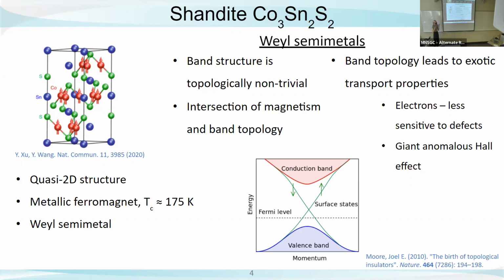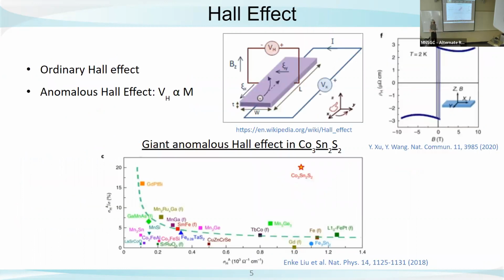And another thing that comes with Weyl semimetals is this giant anomalous Hall effect. And so a little bit on this Hall effect. When we measure an ordinary Hall effect, we take that material here in purple and we run a current through it. And then we apply a magnetic field and measure a Hall voltage transverse to that current that we're sending through it. And when we would get an output of magnetic field versus Hall signal for our ordinary material, you would see that it was linear because you would just have the magnetic field that we're applying.